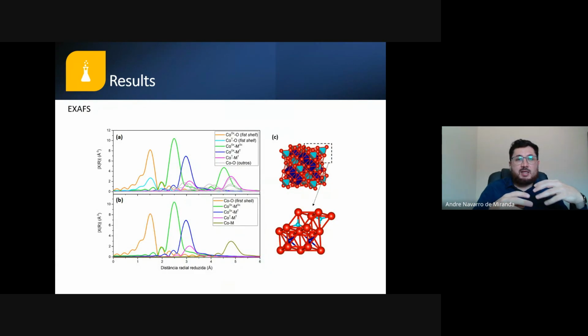We have performed some EXAFS analysis of this process. EXAFS is a kind of X-ray absorption experiment. And when we do that, we can see here the distance between atoms in angstroms. So we have, for example, the cobalt-oxygen bonds. The cobalt-oxygen bonds are these two. Here we have octahedral and tetrahedral cobalt. So we have these cobalt-oxygen bonds, and it's the first shell here. We also have the cobalt octahedral to cobalt octahedral distance here. We also have the cobalt octahedral to cobalt tetrahedral here. So we start to better understand this distance